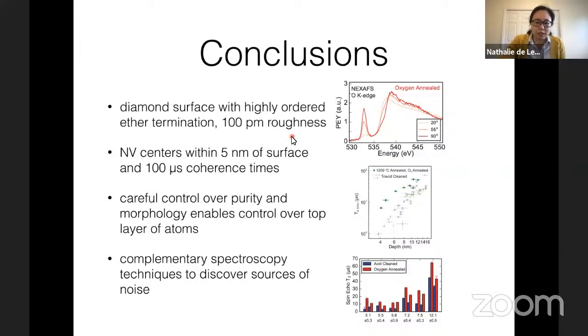Part of the reason that no such chemistry exists is that in addition to being inert, number two is that it has a very, very small lattice constant. Just because you have this extremely sterically hindered environment, it's both hard to attack it with chemicals and it's very hard to fit any groups on it. So you just don't have access to that many types of termination. And then the third issue is very prosaic. It's just that it's extremely hard to polish. It's the hardest material in the world, and polishing diamond is more like this horrible war of attrition where you kind of bang diamond against a wheel that is impregnated with more diamond. So it's a whole art in and of itself, just getting smooth surfaces to begin with.